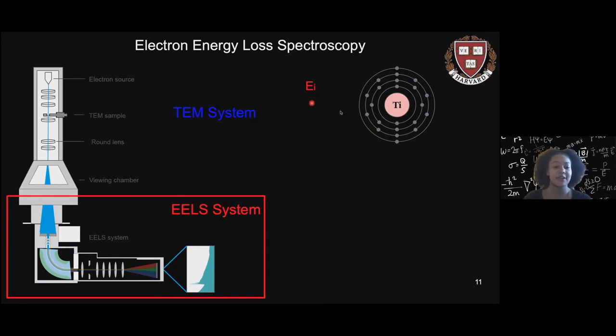The amount of energy that the electron loses can be detected and measured using an electron spectrometer, and we can interpret what atom was present as a result of this energy loss. So this electron with energy EI may hit the titanium atom, and as a result of the collision, knock off an inner shell electron from the titanium atom. As a result, we're able to measure exactly how much energy our initial electron lost by then capturing the electron on the other side of the sample and measuring the energy.